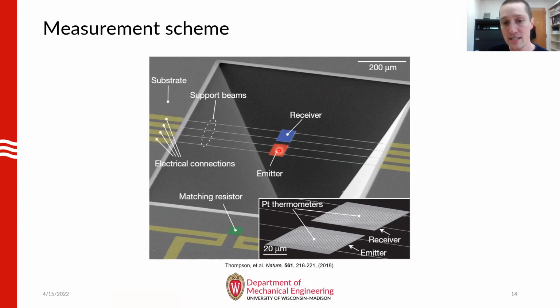If you look at the inset, you can see that each of the membranes has an integrated platinum line as well, which can be used to heat up the emitter, here false colored in red, and measure the temperature rise of the receiver, here false colored in blue. To investigate the effects of small dimensions on the heat transfer, I fabricated different sets of these devices with various thicknesses, which ranged from 11 microns thick all the way down to 270 nanometers, which is much smaller than that peak thermal wavelength.